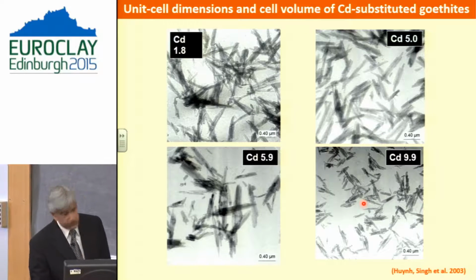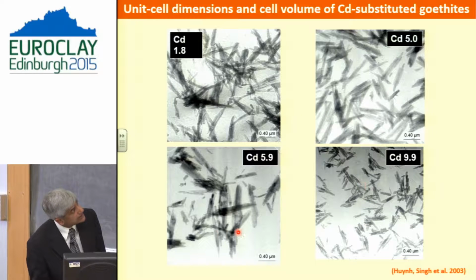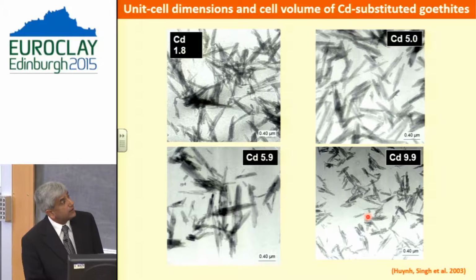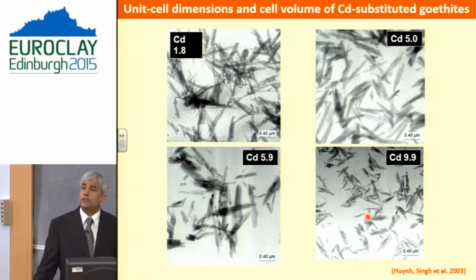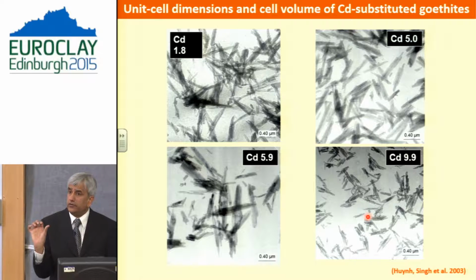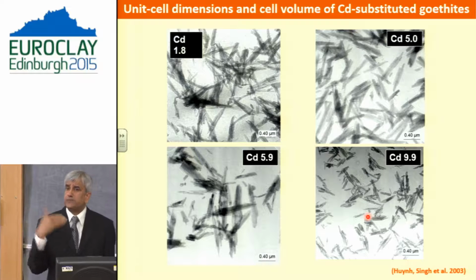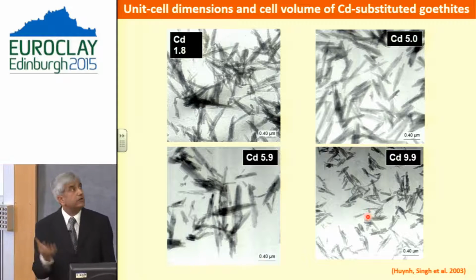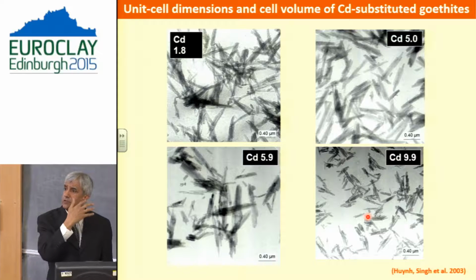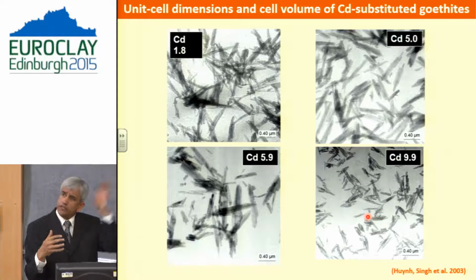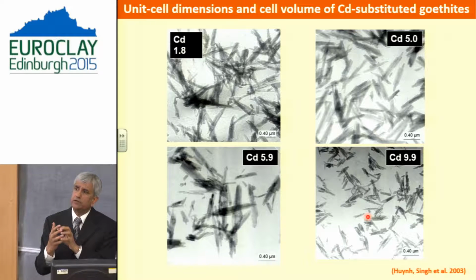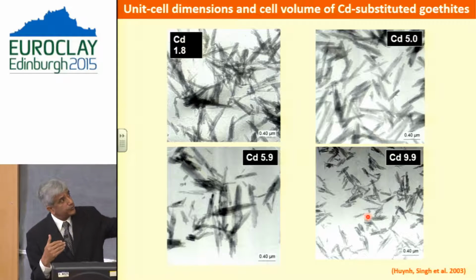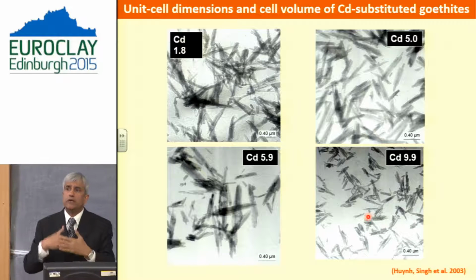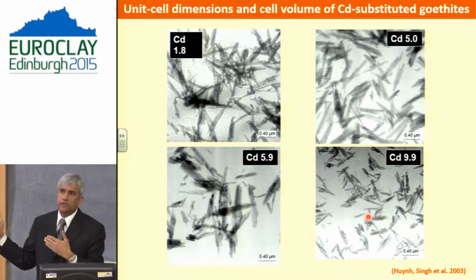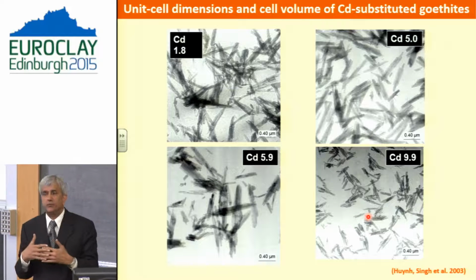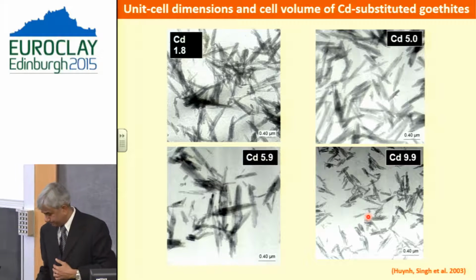And this effect on crystal size was in some way similar to copper, in that the crystal dimensions decreased. So crystals become much smaller, specific surface area becomes much larger, and you can start seeing the implication of this: the cadmium gets incorporated in the structure, but if you have goethite produced with the cadmium substitution, that will have much higher specific surface area and much higher reactivity compared to pure goethite.